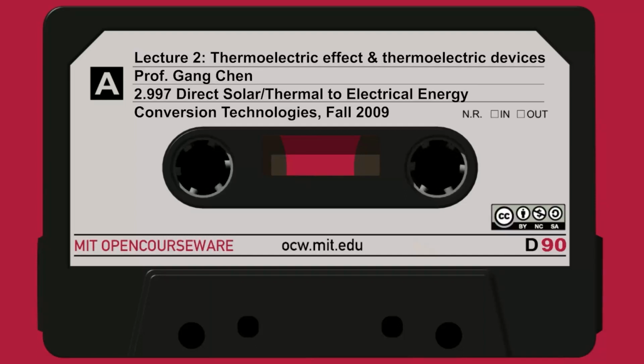Now, if I think about Joule heating, the difference from conduction is this: this side is hot, this side is cold, heat goes by conduction. The Joule heating is uniformly generated along the leg as an approximation. So in that case, about half of the Joule heating goes this way, the other half goes the other way. You can solve the equation, you'll find that's the answer. But that's the intuitive argument also. So in that case, the real leg cooling I have, in addition to Peltier, has half of the Joule heating, this is the electrical resistance, and I have a reverse heat conduction, that's the thermal conductance of the two legs. So that's the mathematics: the electrical resistance is proportional to the resistivity of both legs, area, length, and here the thermal conductance, they both, P and N, combined together. Okay?